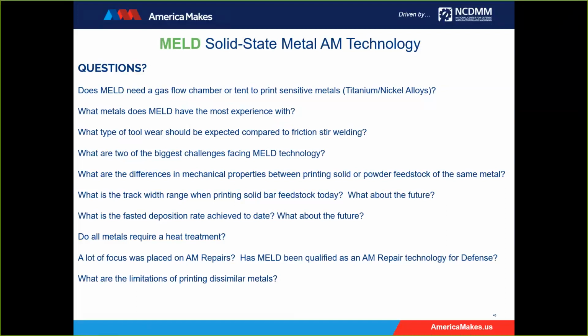I would say we've got a handful of R&D type formulas. Some balance out yield strength, tensile strength, and elongation. Others bump up yield strength and ultimate tensile strength at the expense of elongation, and then one is, I'm getting off track. So just a family of heat treat protocols that we would develop together, because we just can't provide those open source given the fact that these were developed with our partners. So yeah, a lot of ways to spin this to zero in and do material development, and then print it onto an application and move it from there.